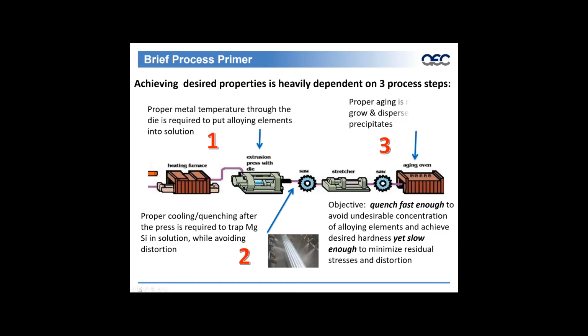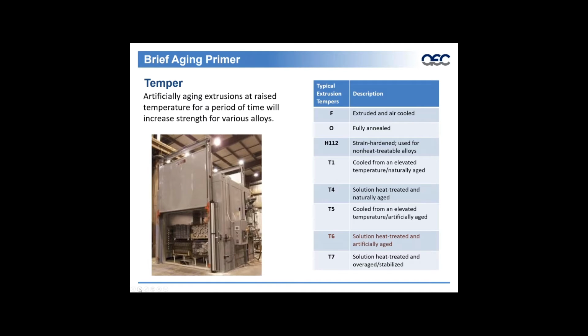The third critical part of the process is proper aging required to grow and disperse the precipitates. And those age ovens, while in the same location as the extrusion operation, are offline from that operation. So temper, artificially aging extrusions at raised temperature for a period of time will increase strength for various alloys. A lot of the tweaking can occur during the age practice, and age practices can range from 5 hours to, let's just say for discussion purposes, 12 hours for a 6000 series alloy.